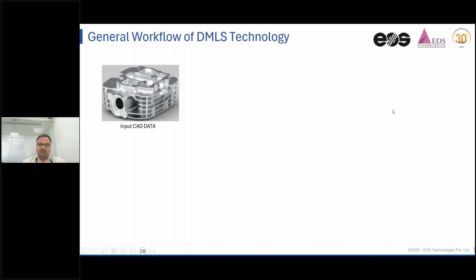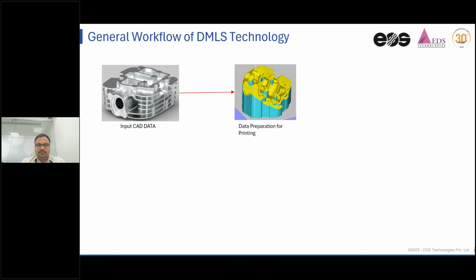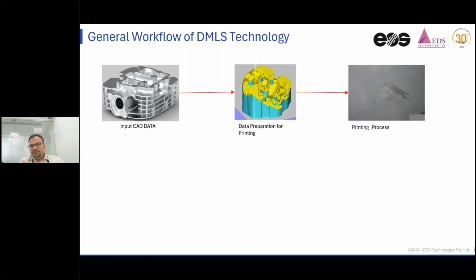So the general workflow of DMLS technology, if you want to understand, I've taken an example of a cylinder head here. You have an input in CAD data form, and then we take that CAD data into the data preparation software. It can be Magics software, or maybe NetFabb software. We do the orientation of the part in metal. Most of the time, metal orientations are preferred to be manual, with experienced application engineers, because it requires attention to heat transfer and other complexities in metal printing. And that is addressable using different software again. In data preparation, we do orientation, and we define the support structures that support the process, support the material, and also work as a heat transfer medium. Once the data preparation is done, we slice it and send that information to the printer. The printer addresses those layers and details, scanning and melting, which we call DMLS.